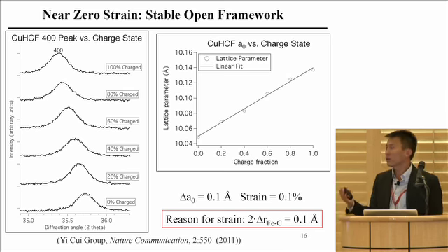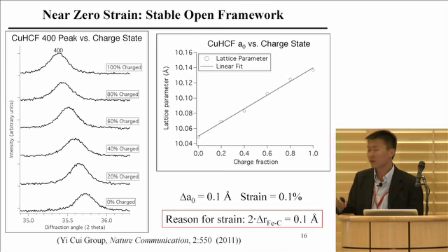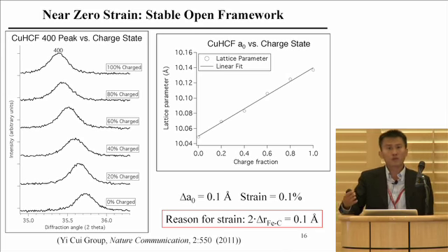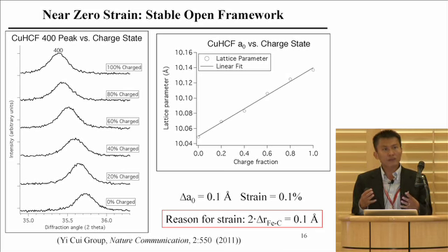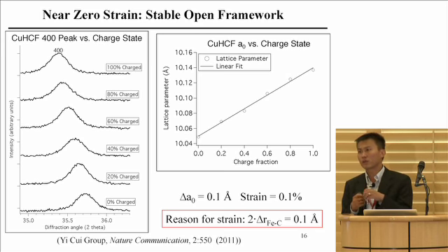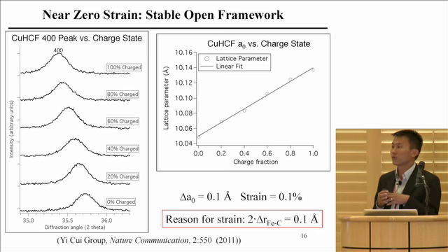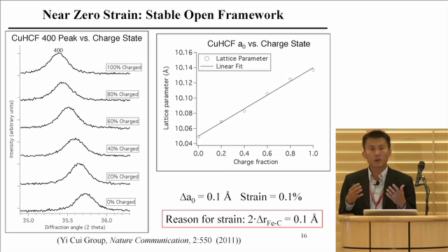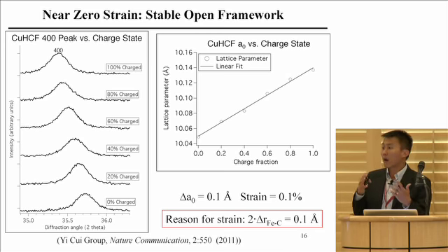That tells you when sodium or potassium ions, in this case sodium, go into the crystal structure, it just fits so nicely. It does not need to expand or contract the crystal structure that much. If you look at the common lithium-ion battery materials you use, carbon or lithium cobalt oxide, you have up to about 8% volume expansion right here.